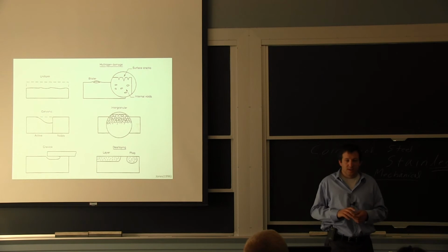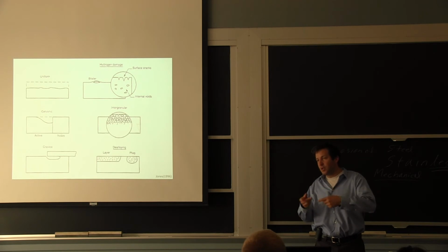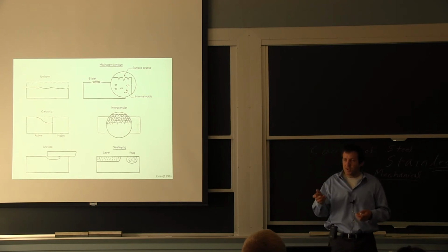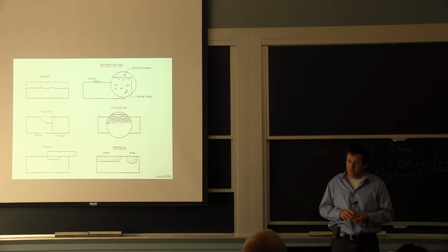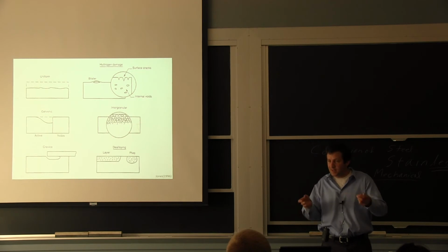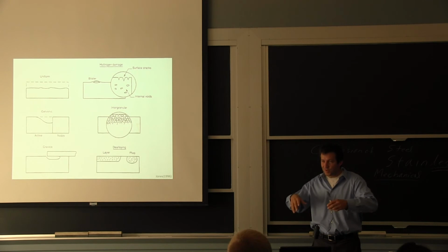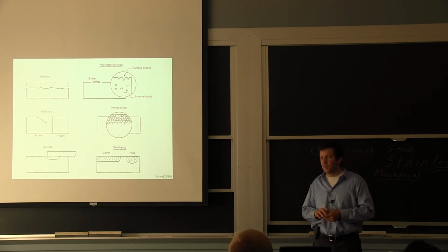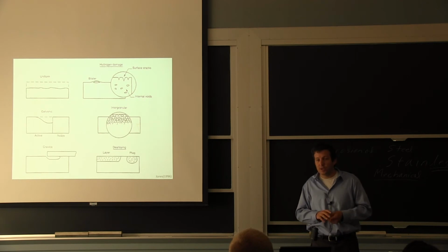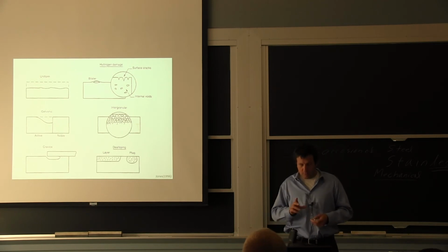So what happens is, not all the time, normally you'll have some degradation of the concrete, changing the local pH, and then you'll have the corrosion of the steel. Not all the time, but a lot of times the degradation actually starts on the concrete side. Obviously, you have some differential in terms of elasticity and expansion that will also make that interface prone to starting the corrosion. But as long as your piece of steel is embedded in the concrete and the concrete is sound, you're good. Even if the oxygen gets to it, it's not going to react because you have a higher pH. So you passivate. And we'll get to that. It's a good question. Any other question?